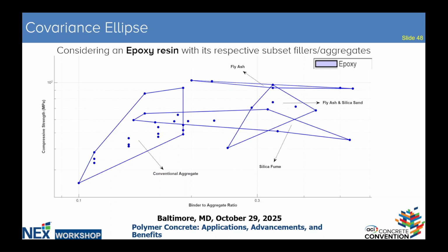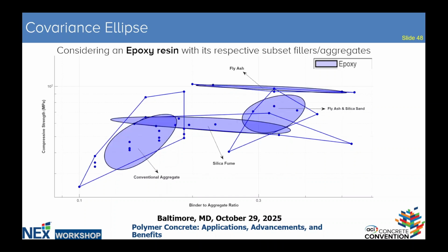We had to fit the data by using the covariance from statistics to see how the data is covarying between the y-axis and x-axis. So for the spread between the axes, you get these envelopes here, where each envelope symbolizes a covariance with an ellipse, which is fitting the data within each boundary. So we have a final ellipse for conventional aggregates, for silica fume, and for fly ash and silica sand. These are the covariance fit data for each subset data.